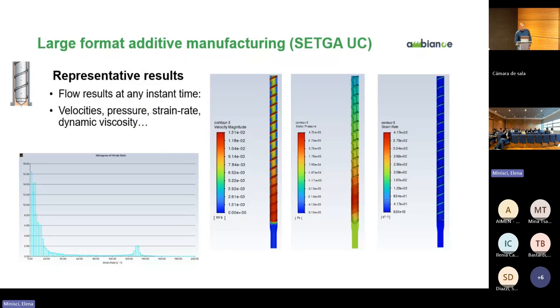Basically, we have full access to the velocity profiles. We also have full access to the pressure distributions, like in this one, where we see that the maximum pressures are in the zones at the end of the screw, where the channels are very narrow. For shear stresses, we can obtain histograms of the shear stress and strain rate distributions in order to see if our characterization